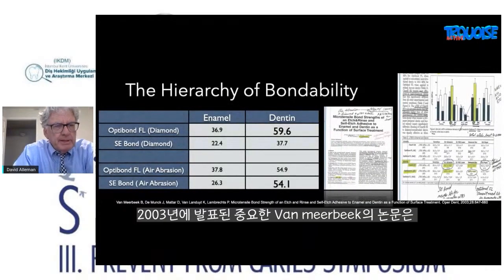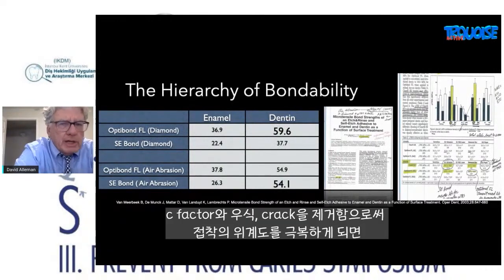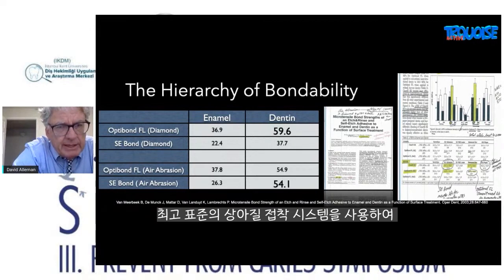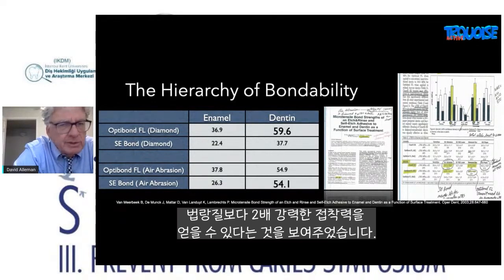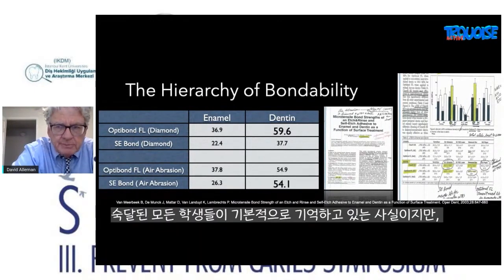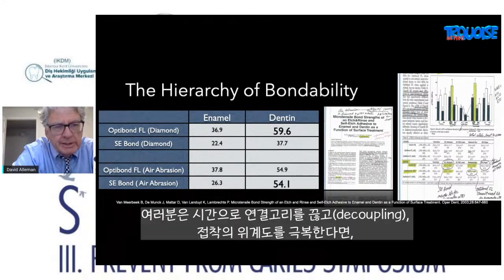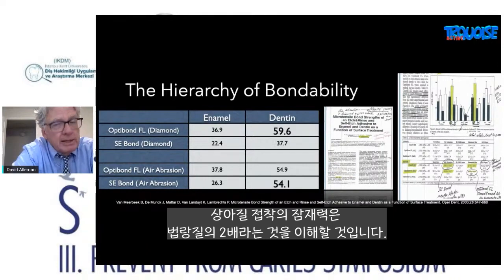And this paper by Van Meerbeek shows that if we have overcome the hierarchy of bondability by eliminating C factor, by eliminating decay, by eliminating cracks, then we have the ability to double the bond strength of enamel with our dentin bonding systems that are gold standard. So this is an important paper published in 2003. It's one that all of our mastership students basically memorize, but you will understand that the potential bond to dentin is twice the bond to enamel if you decouple with time and overcome the hierarchy of bondability.